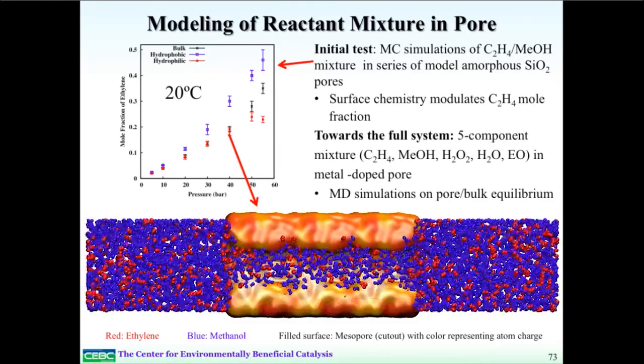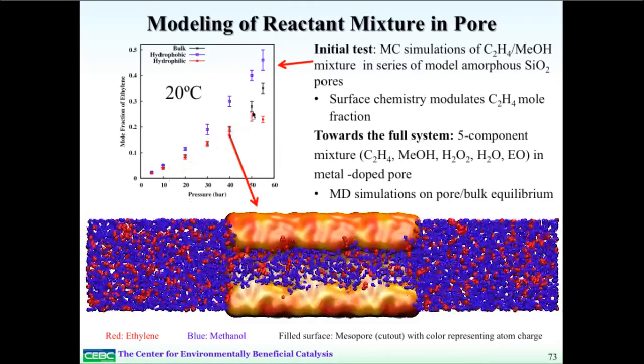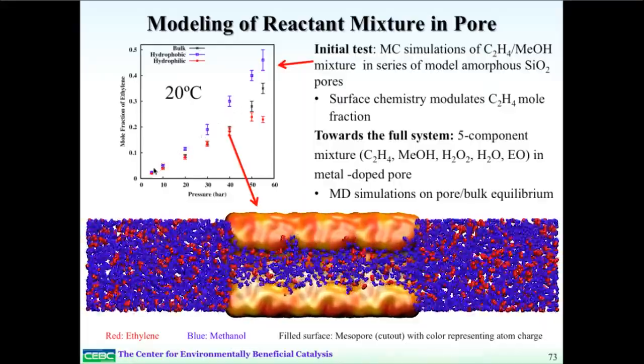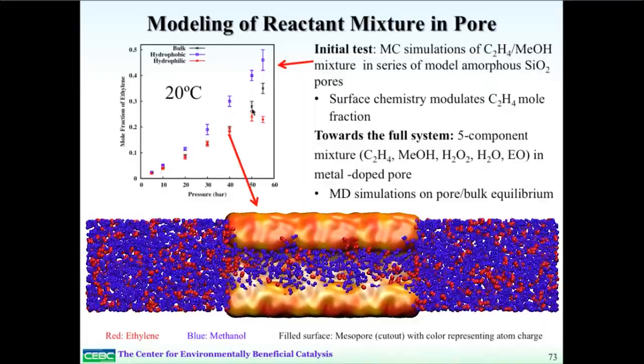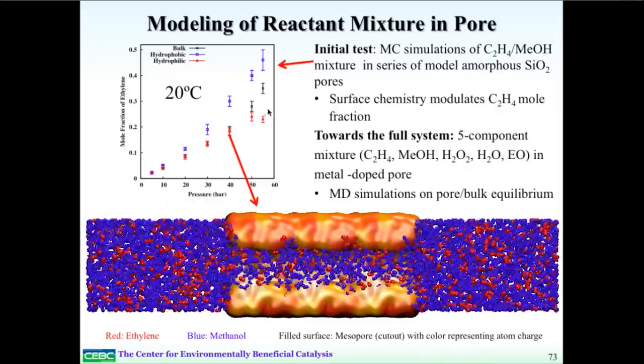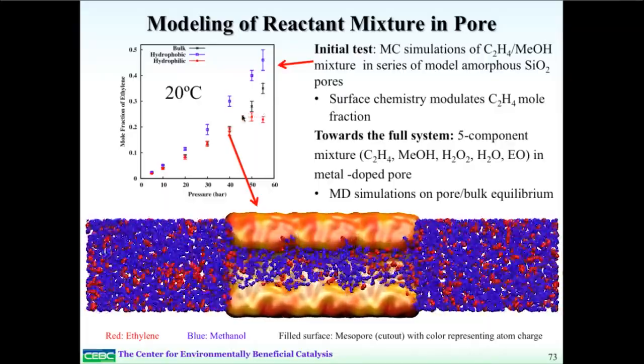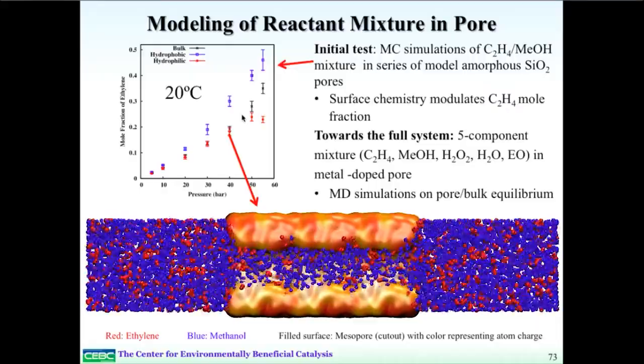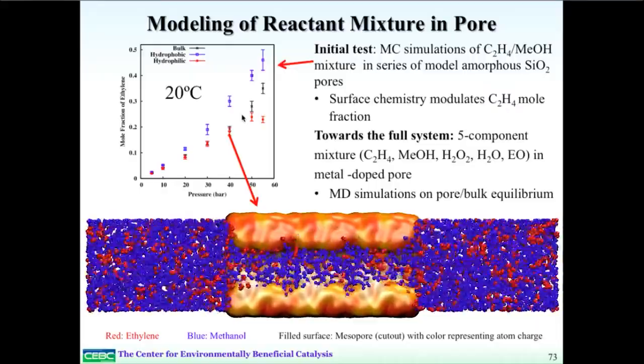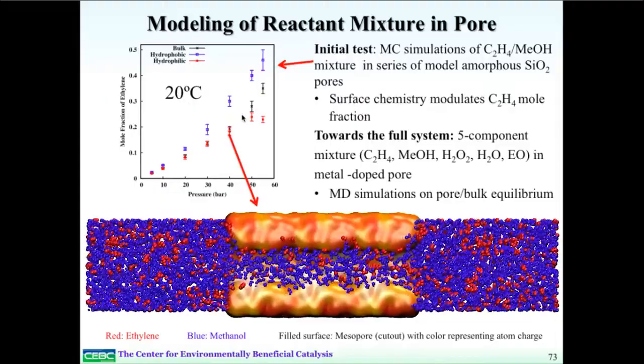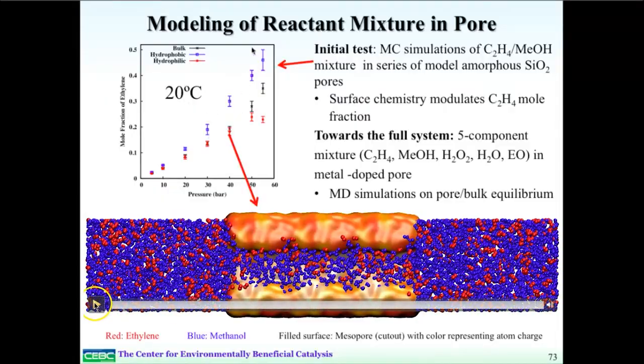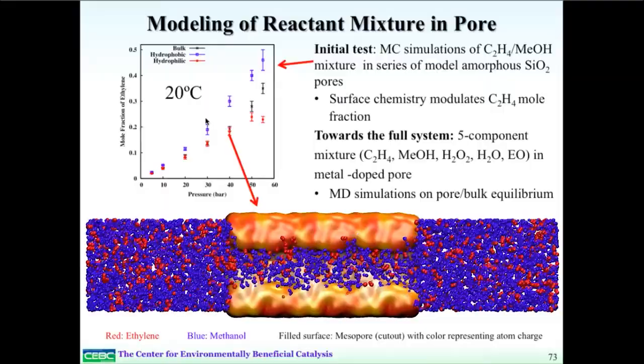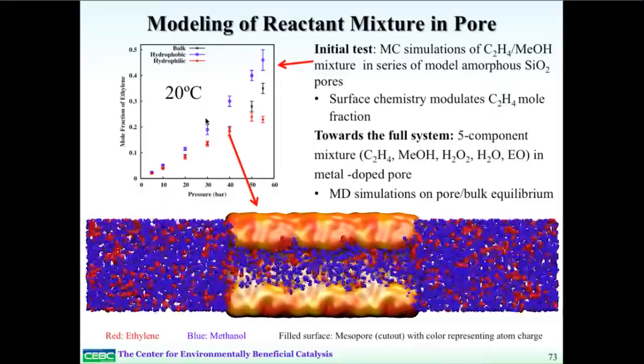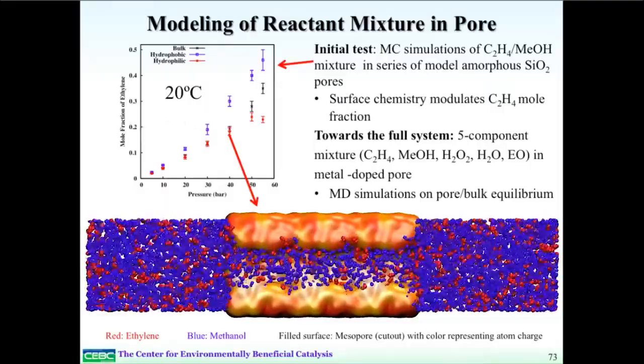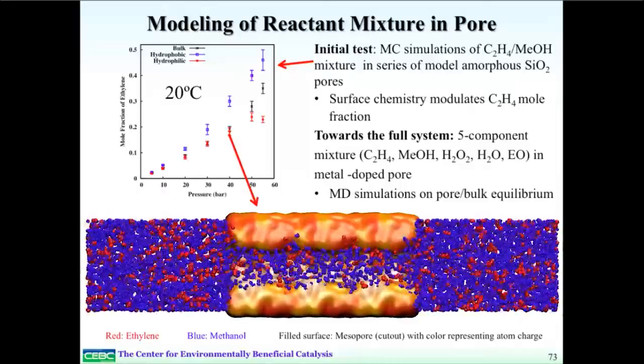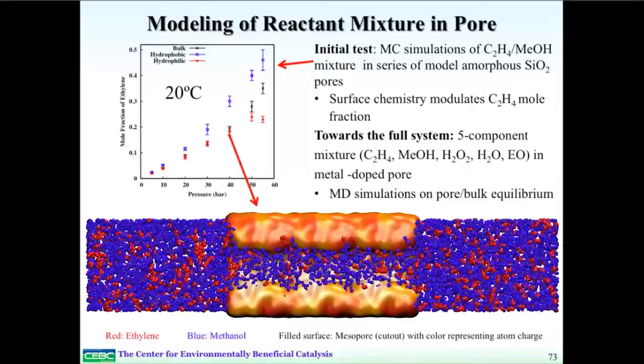And if we go from a hydrophilic site to a hydrophobic site, we can see, for example, these black symbols are the calculations you get in the bulk for the ethylene composition. If you have a hydrophilic pore, one sees that you don't get a big change in the composition of the ethylene of this mixture from the bulk. However, for a hydrophobic pore, you get a significant enhancement of the ethylene composition inside the pore. These are quantities that are very, very difficult for experimentalists to probe, and so the simulations provide us with a lot of phenomenology.